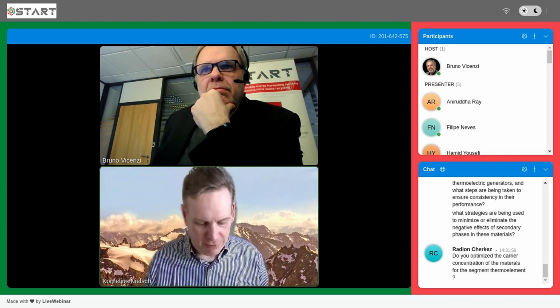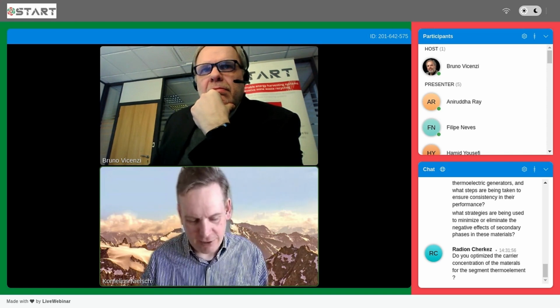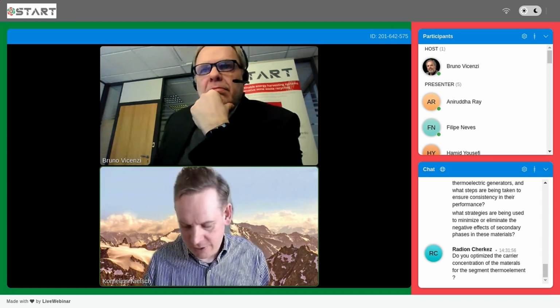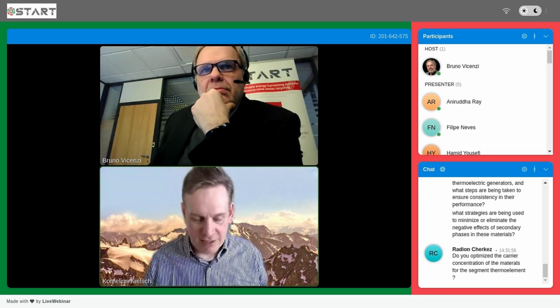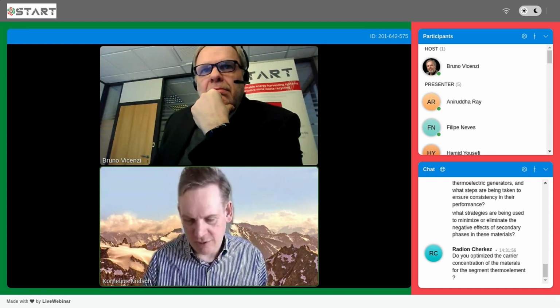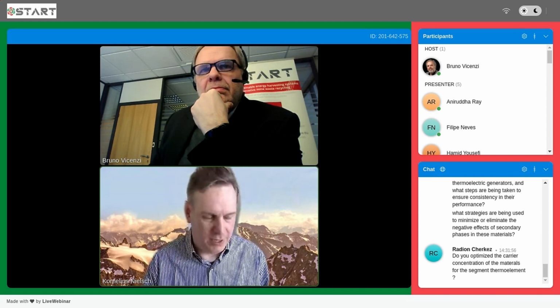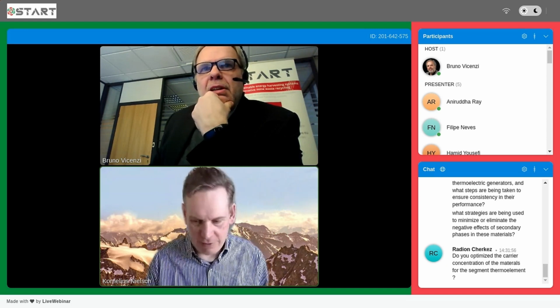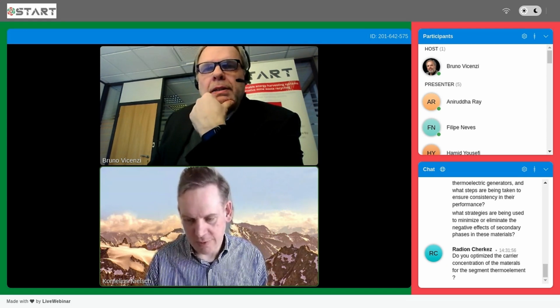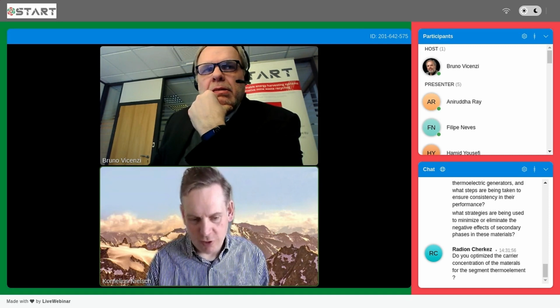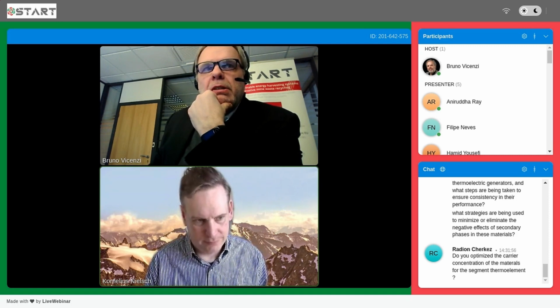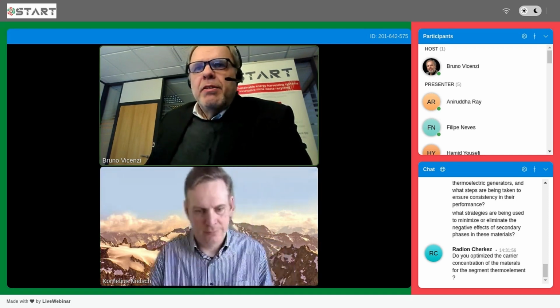So if you buy, for example, a 5.9 pure material, very often it still contains very high percentages of oxygen. This is not covered in this purity. But if you refine it and work with rather pure magnesium, this helps strongly to improve the overall quality.